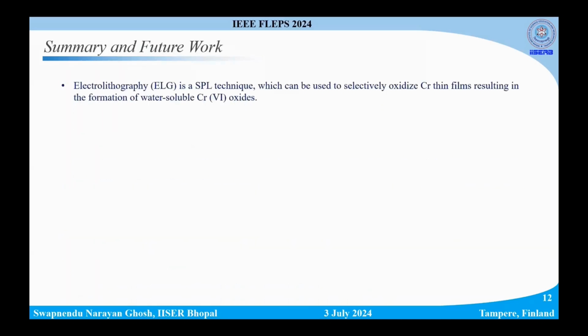So to summarize the talk, electrolithography is a process in which we can selectively oxidize chrome films to create water-soluble chromium 6 oxides. The chromium 6 oxides can be easily removed using water. Therefore, it's a direct and resistless patterning on chromium thin films without using any resist or developer chemicals.